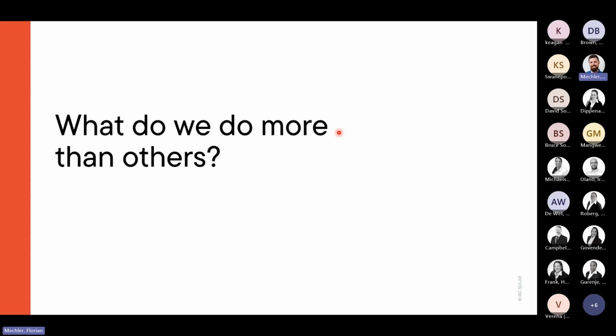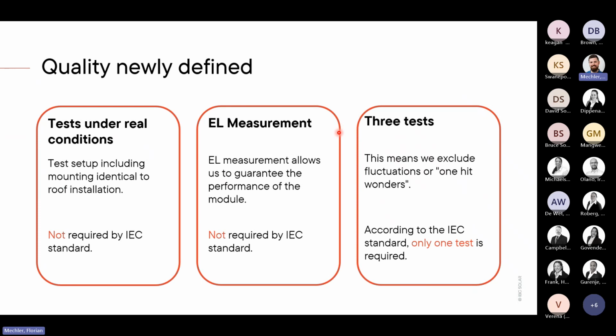So what do we do more than others? We test under real conditions. This is not required by IEC standards. I described it at the beginning of my presentation. For IEC, the module makers test the module with what they call super clamps. They apply very high torque on this clamp so that the module cannot come out of the clamp. And we test it under real conditions, for example with our Aerofix mounting structure, with the right torque we use in the field, and so on.